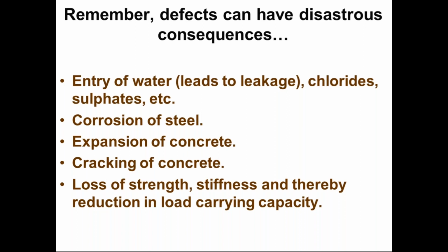And when chlorides attack the steel, corrosion happens. And when steel corrodes, it expands to almost 6 times its original size because of the rust formation. And that results in cracking of the concrete. And the cracking of the concrete results in loss of strength, stiffness, and also porosity increases, thereby reducing the load carrying capacity of the structure. And it can go to such an extent that ultimately,